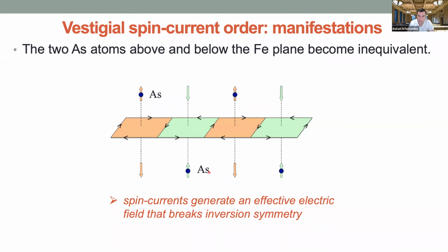So it means that all the arsenic atoms will experience the same direction of the electric field. If you imagine that this arsenic has some charge, it will move not symmetrically with respect to the iron plane. So the key point is that these two arsenic atoms become inequivalent in this vestigial spin current phase.